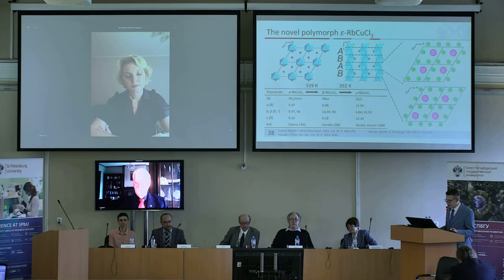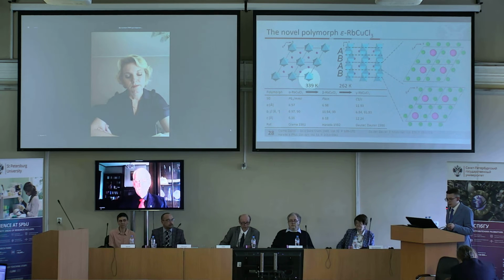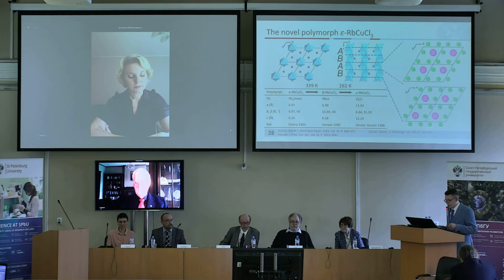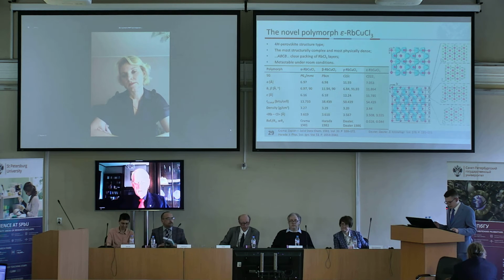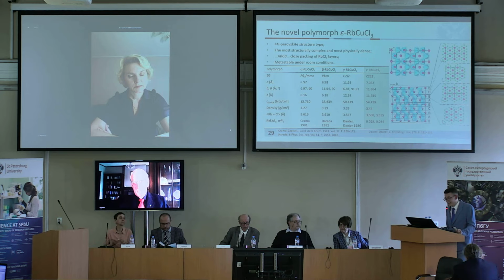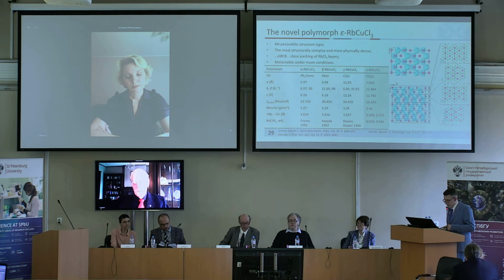All 3 polymorphs are examples of hexagonal perovskites with 2 layers, and the RbCuCl3 layers are organized in the AB-AB sequence. The new polymorph demonstrates a completely different organization. Its structure is an example of a mixed hexagonal perovskite, in which RbCuCl3 layers are packed in the AB-CB sequence. Instead of chains, such octahedra connect through faces.